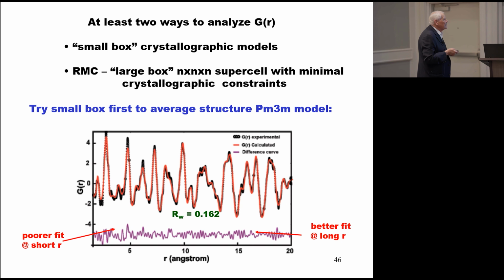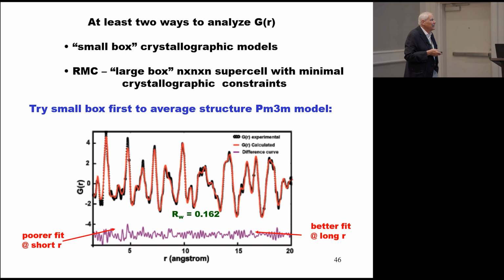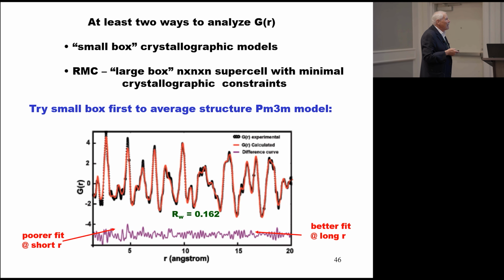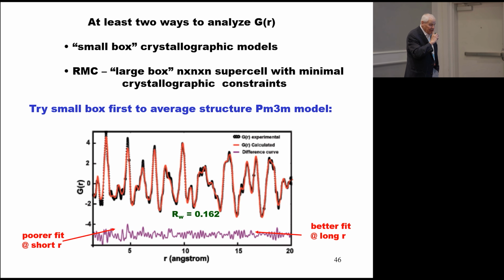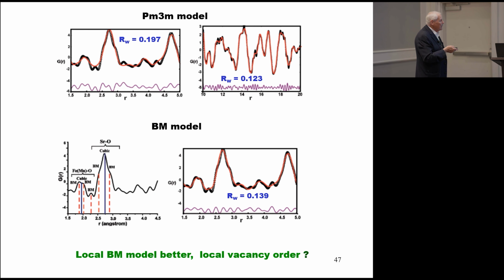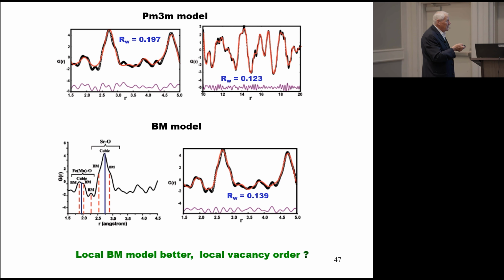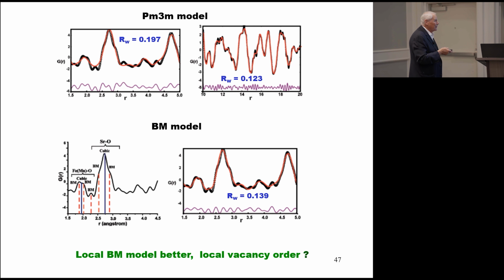Okay, so as we heard this morning, there are at least two ways to analyze the G of R, the small box and the RMC large box approach. The small box approach seems to be falling out of favor, but we did this work quite a while ago, and so we use both approaches. If you try to model the data using the cubic model, of course you've got a remarkably lousy fit, as you would expect.